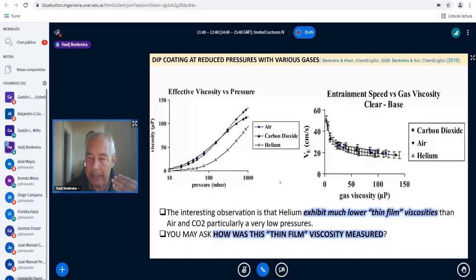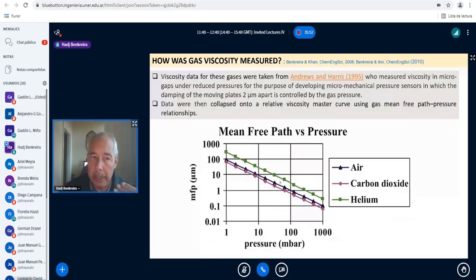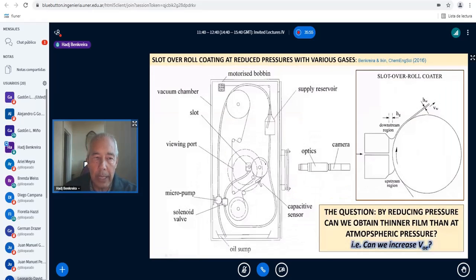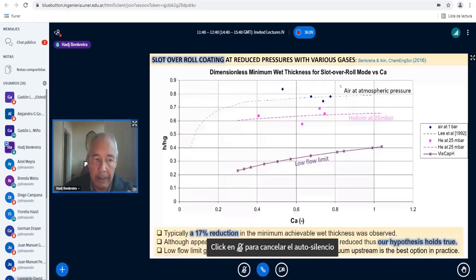But before I get to that, we checked our finding by doing the experiment on gas entrainment using slot coating, and there is the result. At atmospheric pressure, there is a minimum film thickness that we could have. That is the maximum speed that we could reach. And when we used helium at 25 millibar, we were able to coat much thinner. That is, we were able to go at much higher speed. But of course, in this situation, we could not go at very, very high speed.